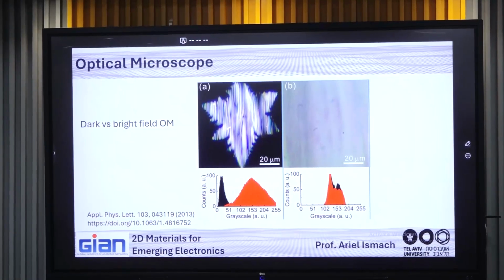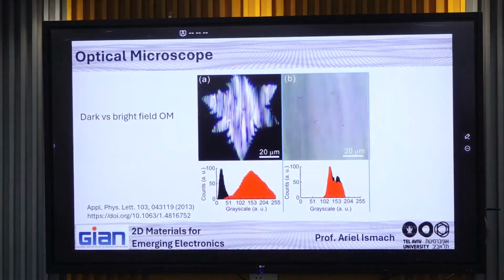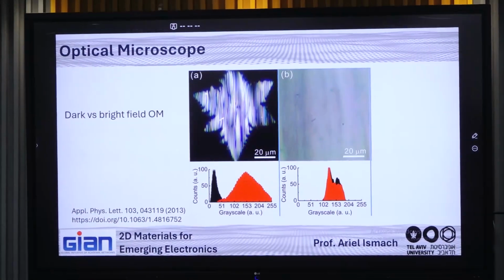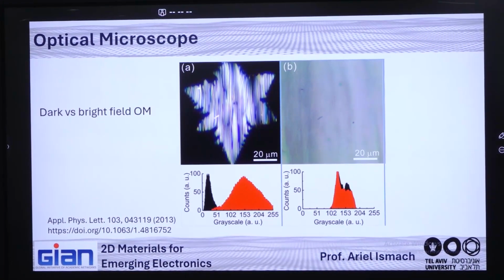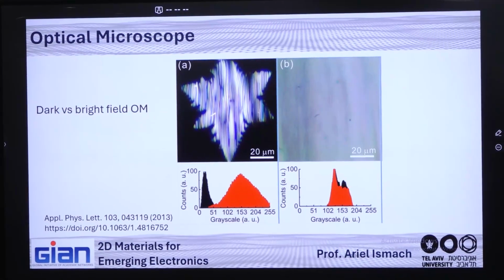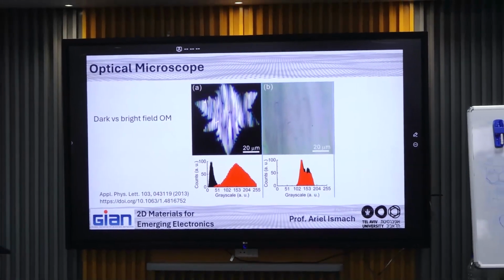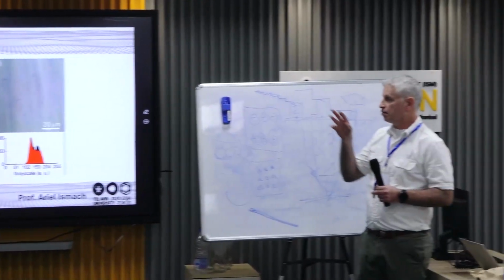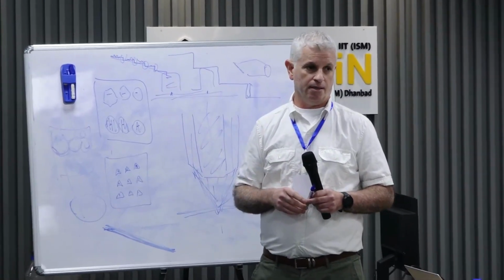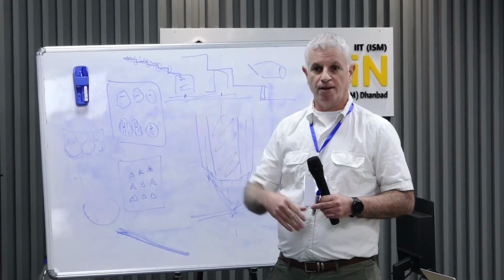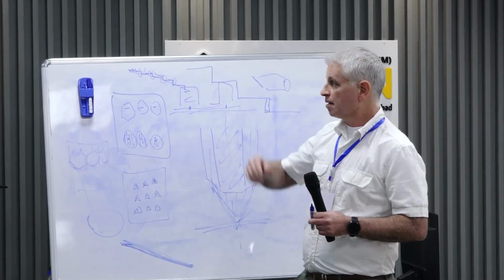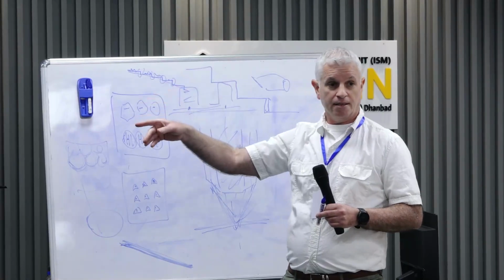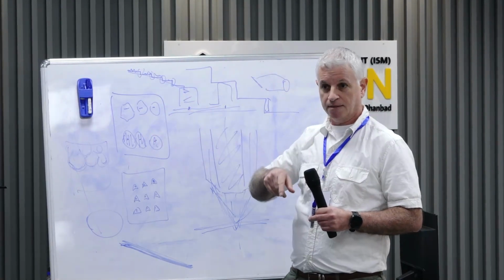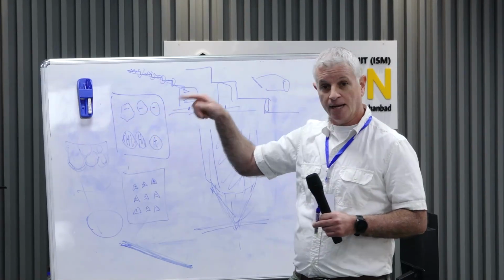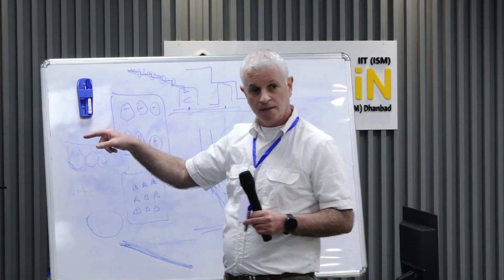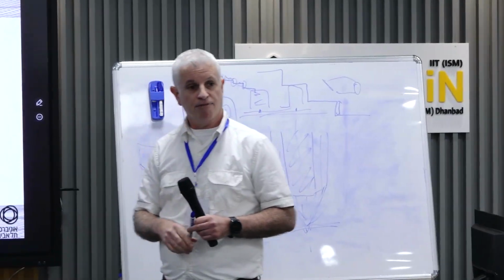Because again, the graphene protects the surface. The graphene stabilizes the steps longer. When you expose the surface to the air, these steps are gone. Even very mild oxidation that we don't see by eye will kill these nanofacets or nanosteps. But the ones that are underneath the graphene are present, and these are the ones that you're seeing here. So again, this is an indirect way to check that we have a graphene layer.